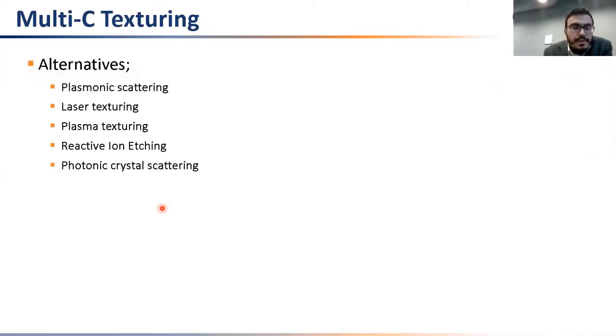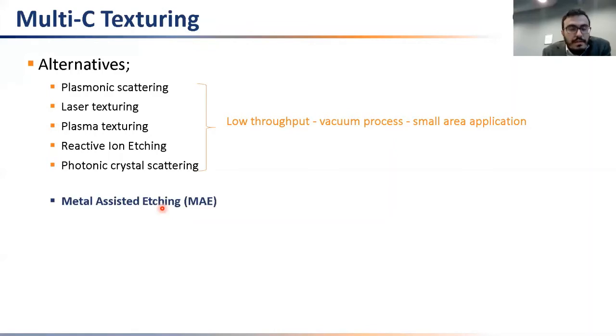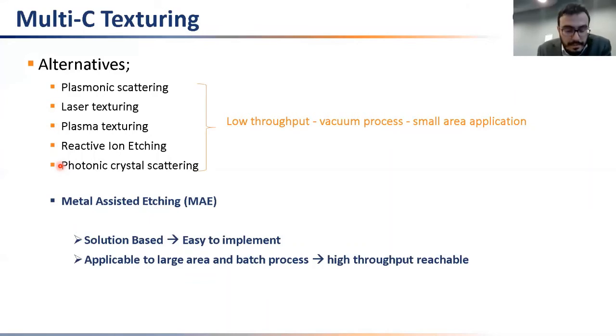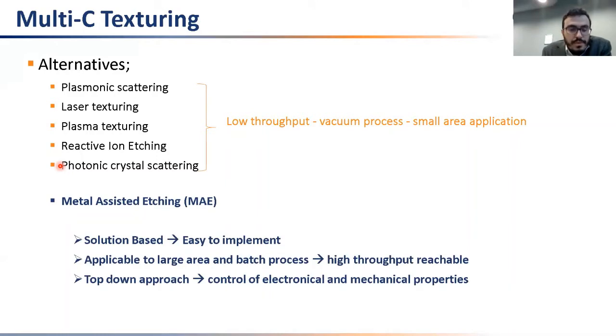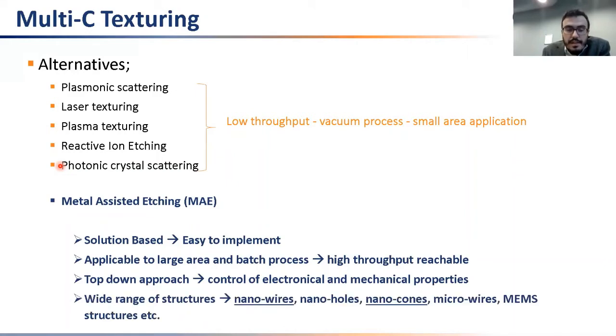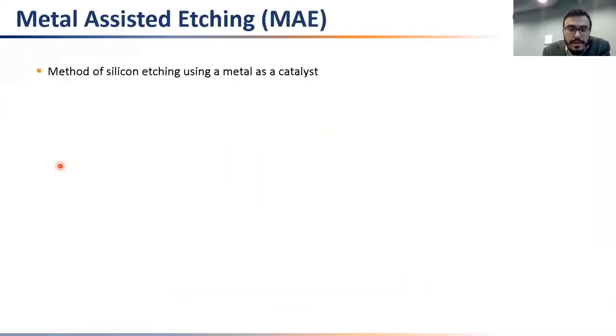So what are the alternatives for texturing of multicrystalline silicon solar cells? We have plasmonic scattering, laser texturing, plasma texturing, reactive ion etching, and photonic crystal scattering methods, which are low throughput and vacuum processes, and they cannot all be applied to large areas, so they are not industrially feasible. However, there is another solution called metal-assisted etching, which is a solution-based method, so it's easy to implement. It's applicable to large area and batch process, so you can have high throughput, and it's a top-down approach for nano processing, so control of electronic and mechanical properties is easy. And you can make a range of structures like nanowires, nanoholes, nanocones, and microwires.